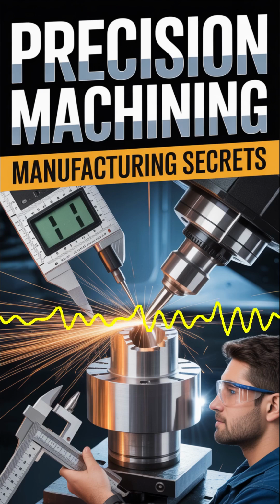So based on the simulation, they built that superior 2-clamp design, and then they had to prove the simulation was right in the real world. How did they do that? They used a dial gauge indicator, which is a physical high-precision measuring tool. This one had a resolution of 0.01 millimeters, or 10 microns. They clamped a real engine block at 40 bar and measured the actual deformation. And the result? The experimental measurement was 16.18 microns.